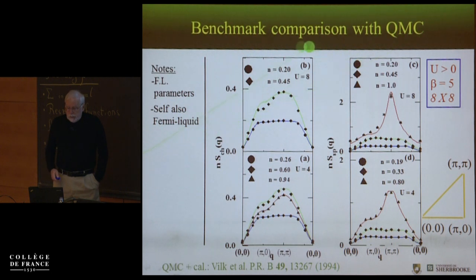So here are the benchmark comparisons with quantum Monte Carlo. There's a lot of things, but we will focus on just a few important ones. We look at relatively large temperature, but the cluster sizes are large enough that we can check that there's no finite size effect. So here is the spin structure. Let's focus on the two bottom panels. This is for U equals 4t, so half the bandwidth. And this is the charge structure factor. Structure factor means just that it is spin at Q times spin at -Q, equal time. So we move along this trajectory in the Brillouin zone, and you see that the spin fluctuations are larger than the charge fluctuations. You have to look at the scale. So it's a non-perturbative regime.